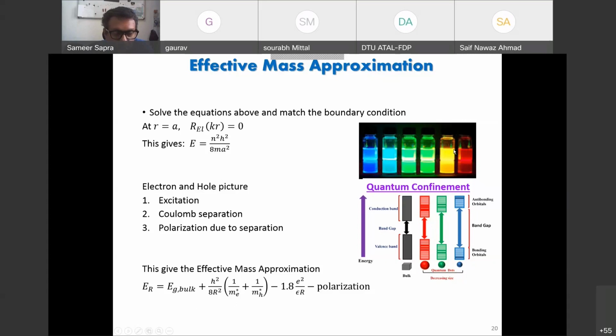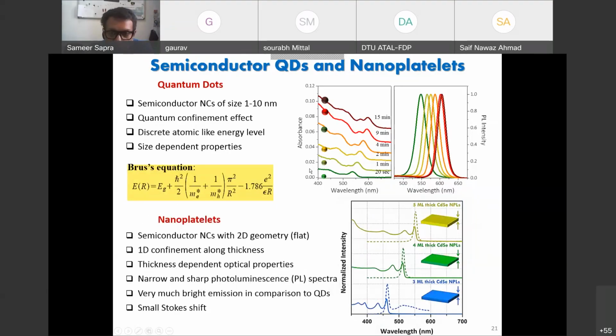So this is again the same picture I showed you initially. This is the small cadmium selenide nanoparticle with a large band gap, and that's a large cadmium selenide nanoparticle with a small band gap. In fact, if you wish to see the absorption spectra of these, you can see how it is shifting towards longer wavelengths. And this is the amount of time that I've kept the reaction for. Longer time allows bigger particles to grow, and the excitonic features shift towards longer wavelengths. So the band gap shifts to lower values as the particle grows. So does the fluorescence. These colors are typically representative of the colors that we actually see.